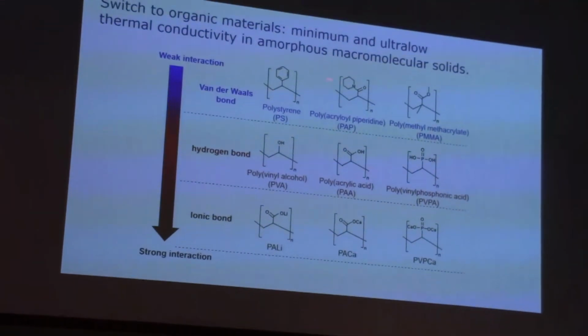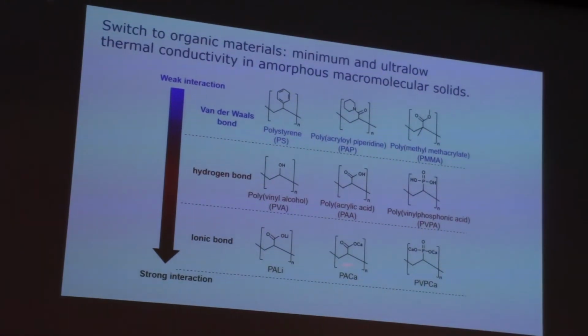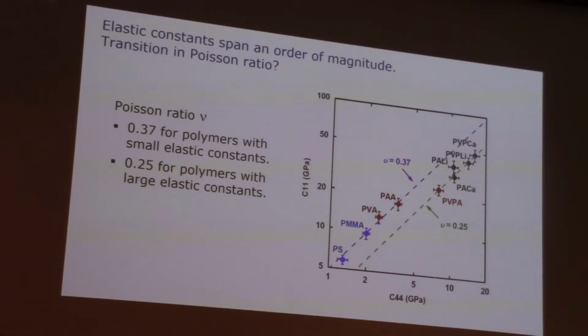So this is just a systematic variation in bonding as we go through materials that are mostly van der Waals bonded, through polymeric materials that are hydrogen bonded, all the way to these somewhat exotic materials, you might call them ionic polymers or ionic polymer salts, where the chains are bonded by relatively strong ionic interactions. Right? So we go through this, and that increases the strength. So we can vary all these things. The postdoc that was working with me on this ended up measuring and reporting in the literature thermal conductivity and elastic constants for almost 30 polymers, over 2 different papers. This gives an example, just from that particular data set.